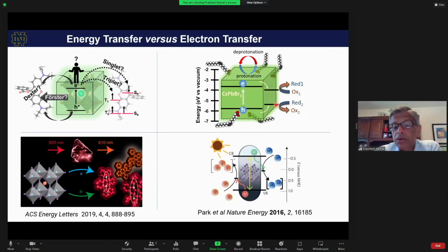In the same way, when it comes to electron transfer, there are several controlling aspects. The more important thing is how nicely the molecule binds and what the energetics are that dictate transferring electrons or holes selectively. Typically in photocatalysis, what one does is take away one of the charge carriers, for example by using a sacrificial donor in a large concentration. That leaves the other charge carrier, for example the electron, a long life to reduce the molecule. Furthermore, the bound ligands can create some problems because they can influence the interaction.